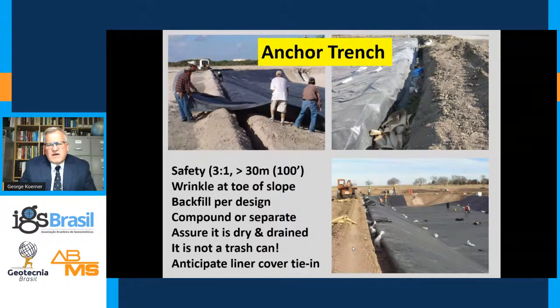We have tremendous weather that moves into locations around the United States. This anchor trench cannot be flooded. The pull-out resistance in a flooded anchor trench is much different than it is in an anchor trench that's been backfilled and very well designed. With this anchor trench, you also have to make sure, is it a compound anchor trench or is it a solo anchor trench? A compound anchor trench will receive many different geosynthetics. In addition to that, the anticipated liner cover tie-in. Some facilities have a cover geomembrane tying into a liner geomembrane to totally envelop the waste. If this is not done properly, it certainly will be an installation headache.